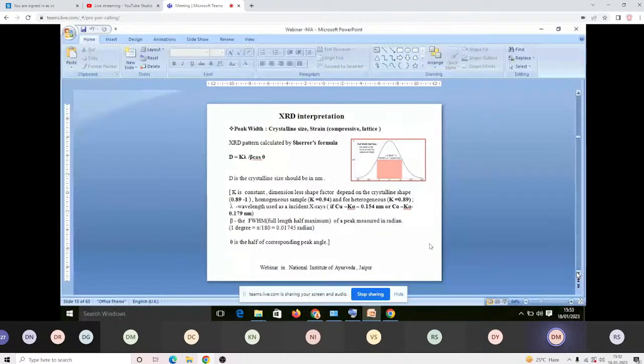XRD interpretation. You can use this formula to calculate the crystalline size of the particle: D equals K lambda divided by beta cos theta. This is the crystalline size, and the unit should be nanometer, and K is a constant here. When the crystalline shape is considered, K is 0.89 to 1, with 0.94 for homogeneous and 0.89 for heterogeneous.